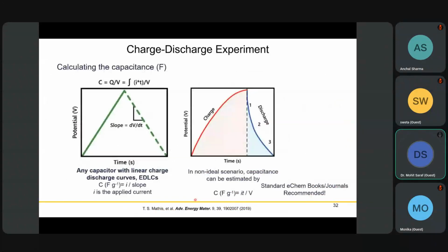When we observe the data, if it is a double layer behavior, you will see a symmetric charge and discharge curve with no slopes, basically a straight line. So you can calculate the capacitance using the formula of current divided by slope, because the slope will be constant at every point in this discharge curve.